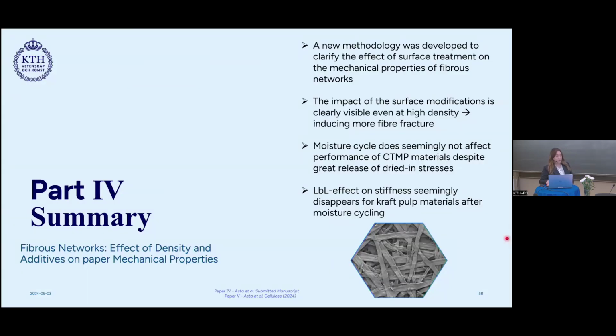So as a summary for part 4, a new methodology was developed to clarify the effect of surface treatment on the mechanical properties of fibrous networks. The impact of the surface modifications is clearly visible even at high density, inducing more fiber fracture. And moisture cycling does seemingly not affect the performance of CTMP materials despite great release of dried-in stresses. And the LBL effect on stiffness seemingly disappears for kraft material after moisture cycling.